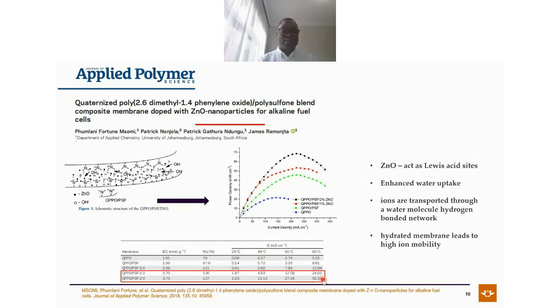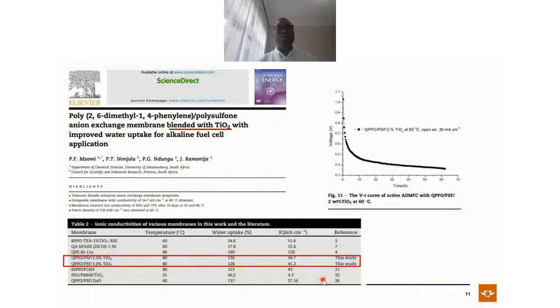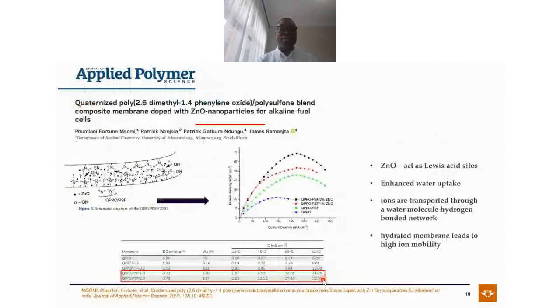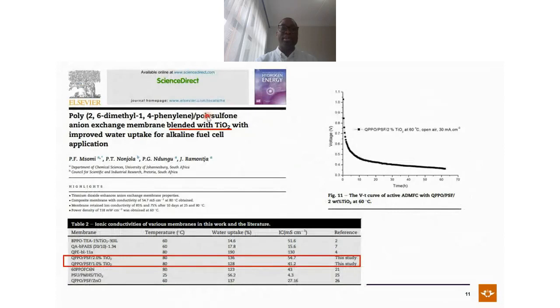But you'll see, the more we've improved this membrane, the more we're getting enhanced and very comparable ion exchange capacity and ion conductivity. Well, after we've looked at zinc oxide, as you can see, zinc oxide has one oxygen, so it's a metal oxide. Then we decided to take titanium dioxide, so this is a metal dioxide. The other one has one oxygen, the other one has two oxygens. So we want to see, will that make any difference? Well, theoretically, it's supposed to make a difference because the dioxide should be able to create a bigger network within the water molecules, which leads to better transportation.